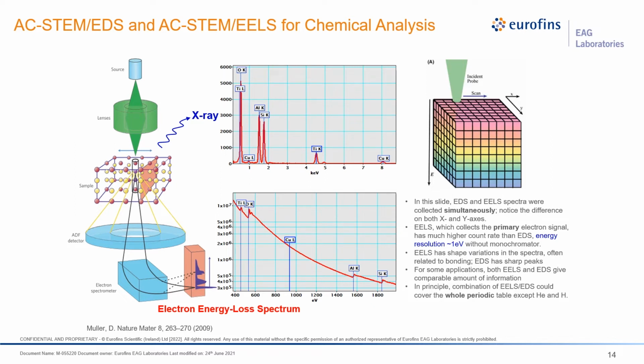and this is called electron energy loss spectroscopy. So we're looking for the subtle losses as those electrons interacted with the sample. We can plot that out, and we can once again understand the composition. But in the case of EELS, we actually also have the ability to further interrogate these specific edges themselves, and they contain information about the localized chemistry within the sample.